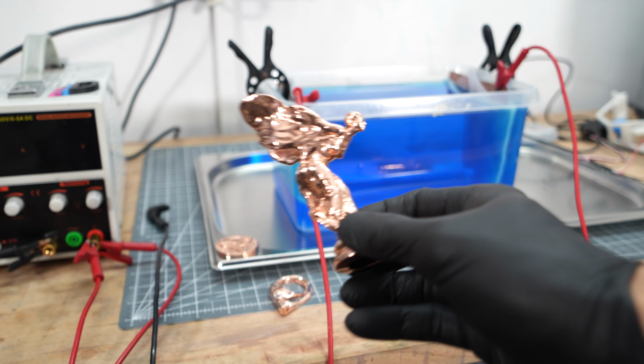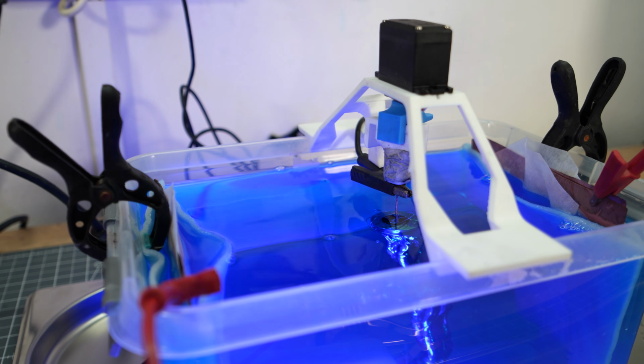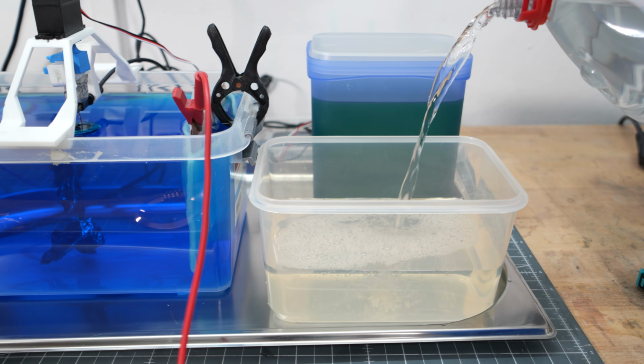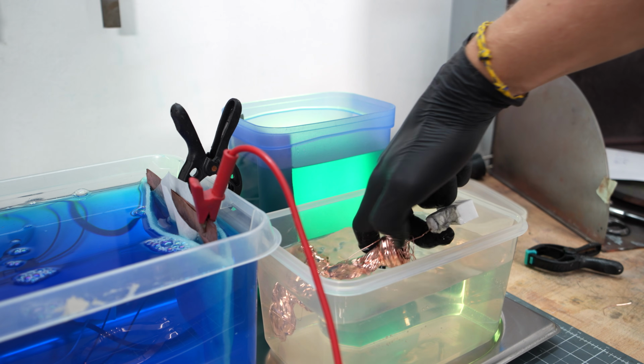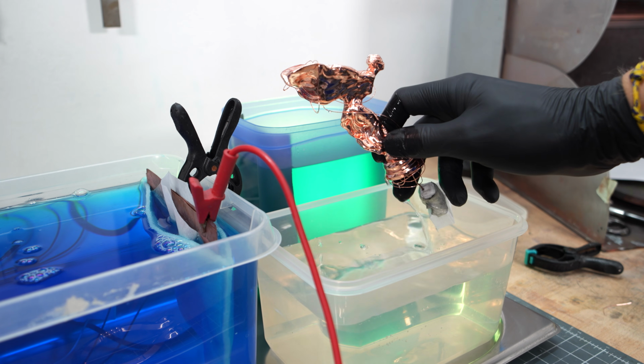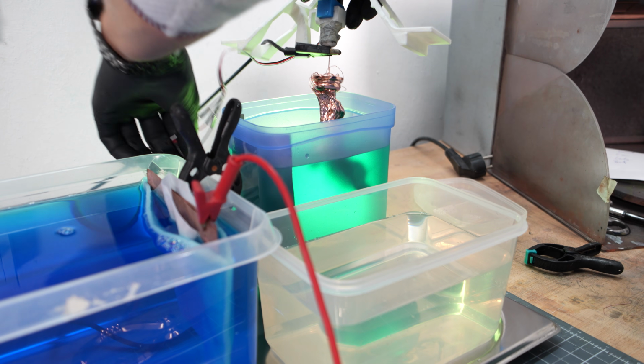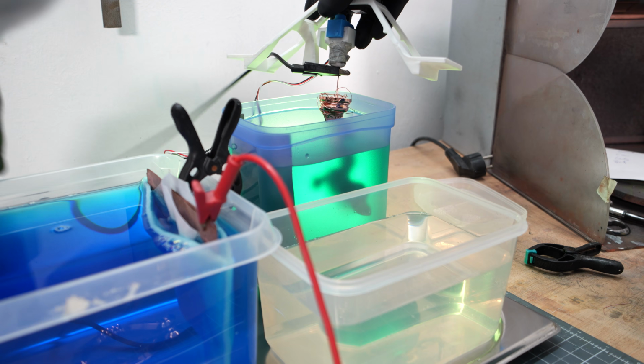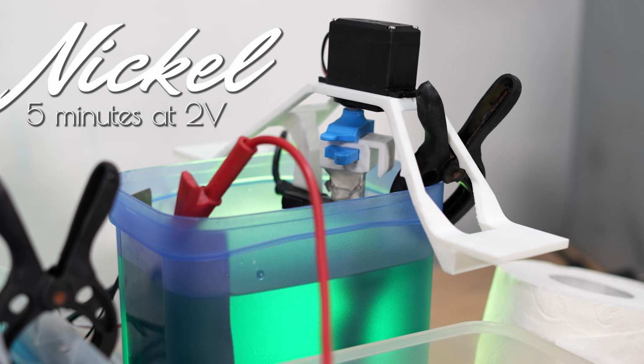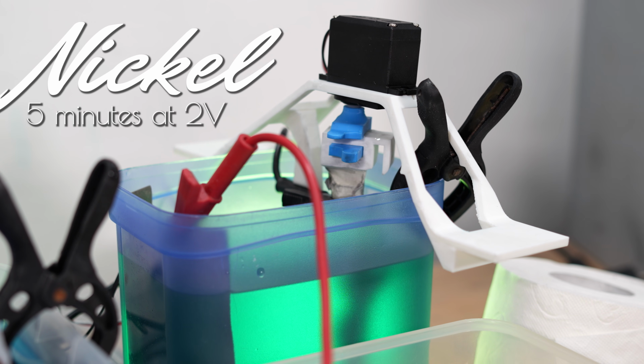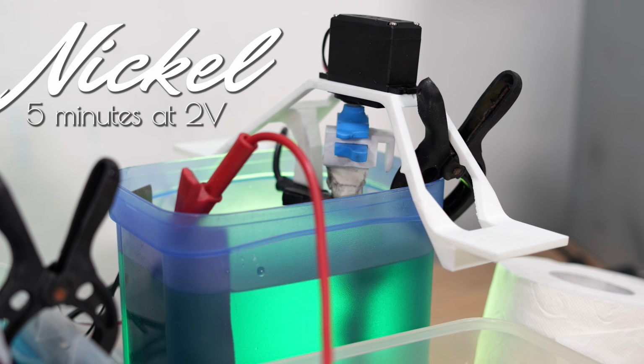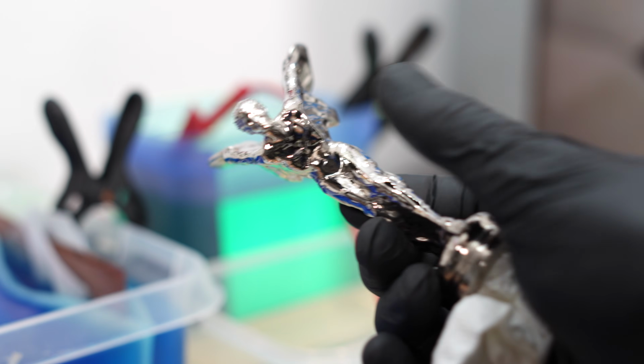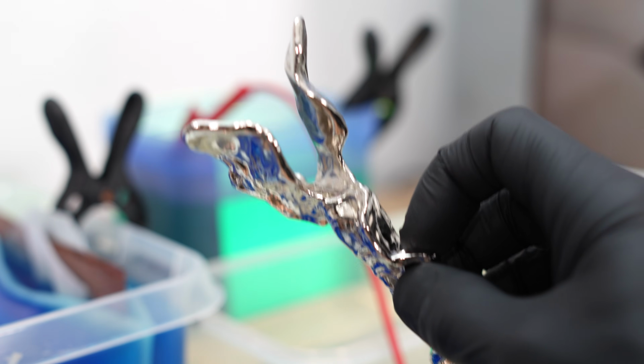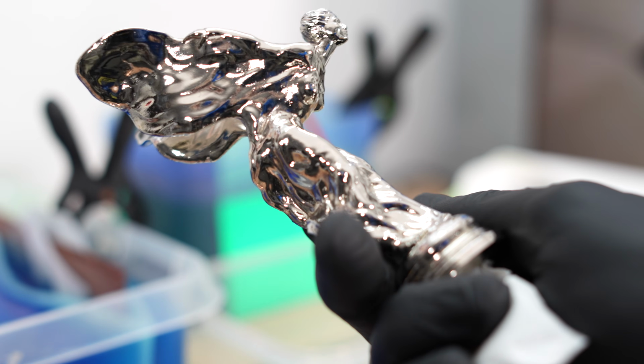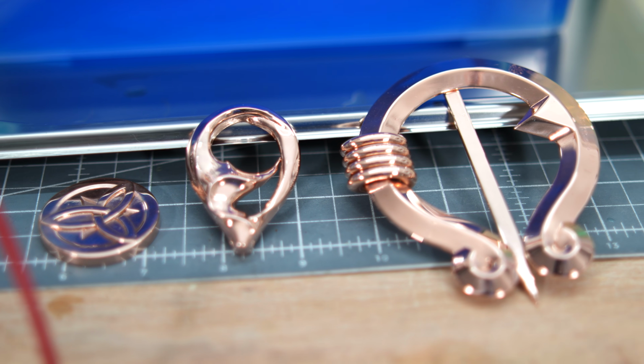So the flying lady is going for one more quick dip in the copper bath just to let that final shine settle in. I've got a bowl of distilled water prepared for rinsing off the copper electrolyte. After that she's taking a spin in the nickel electrolyte at around 2 volts. In about 5 minutes everything's done and ready, and we can rinse off the nickel electrolyte as well. We're doing the same routine for all the parts now.